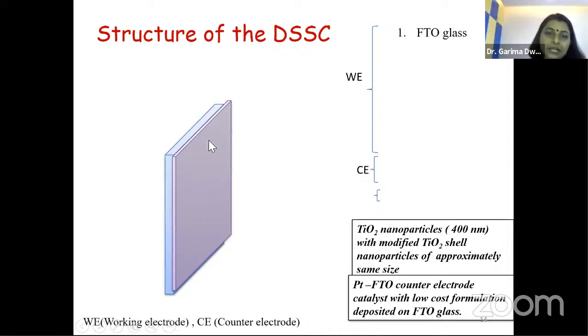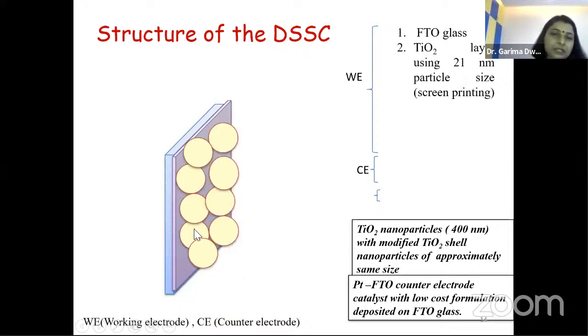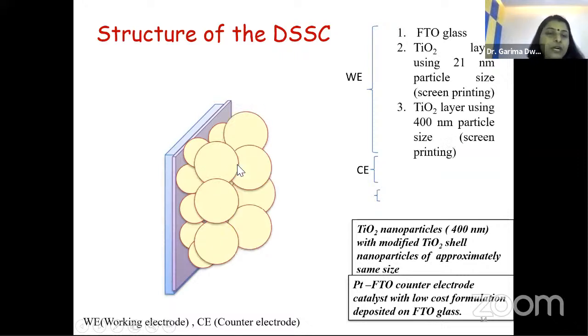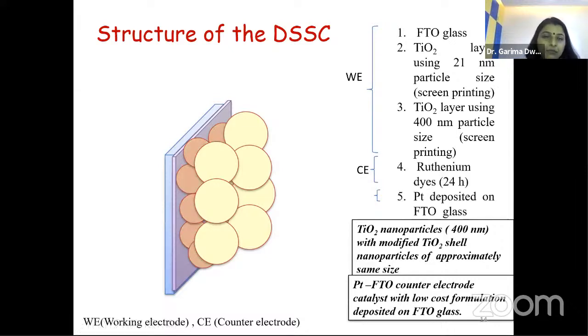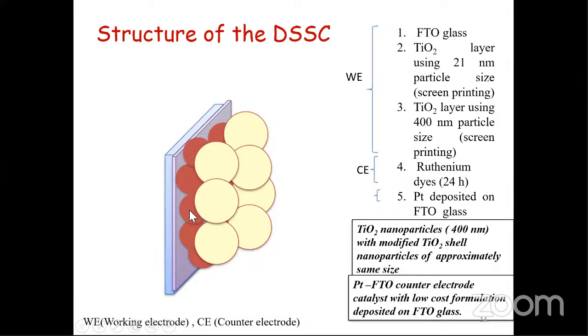And we deposit a layer of TiO2 nanoparticles. We make the paste formulation and deposit this TiO2 nanoparticle layer, on top of which we deposit a layer of 400 nanometer particles of the same semiconductor nanoparticle. Once we dip this electrode in the dye for 24 hours, you can see these particles are very small in size, so the maximum dye is absorbed on these particles.